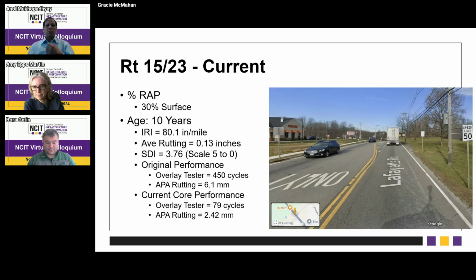Next slide, please. There's another project with a relatively high RAP content of 30% at 10 years. You can see here that the overlay tester results have dropped below the thresholds, but still it's a 10-year-old project. The surface distress index is still not indicating anywhere close to 2.4 for any rehab to be done.